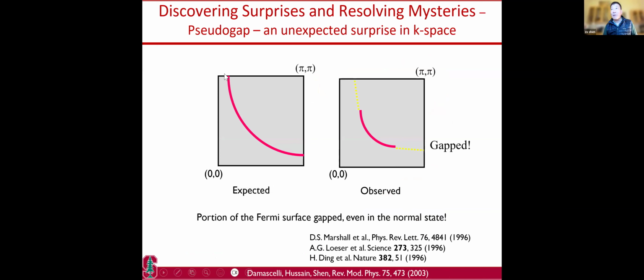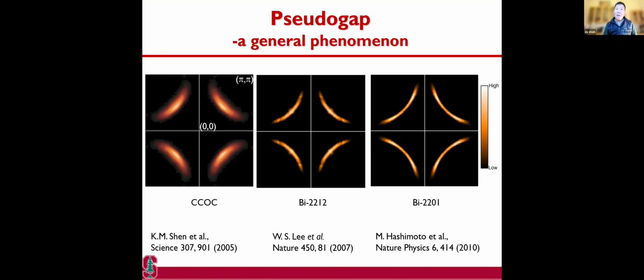The Fermi surface is a topological concept, namely the volume enclosed by the Fermi surface tells you the number of carriers in the system. But early on, almost 3 decades ago, it was found that the Fermi surface stopped in the middle of nowhere. Since this is a volume concept, it cannot stop in the middle of nowhere. So one can think of the yellow region as being gapped. This is one of the persistent questions of the field. It's a common phenomenon; for example, you see it in CCOC, and in underdoped Bi2201 and Bi2212, the single-layer and double-layer systems. So this is a generic feature in the Cuprate problem.